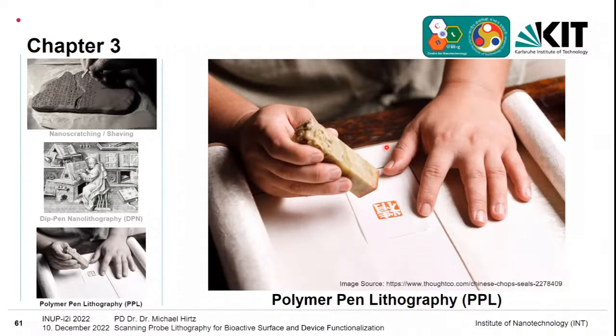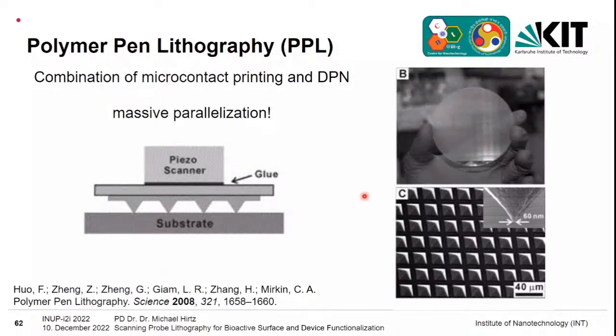Of course, many other places in the world also used stamps, like wooden stamps. And again, we try to miniaturize this and gain control over it, even in the micro or even in the nano realm. This leads to the so-called polymer pen lithography. It's a combination of micro contact printing, which you may be familiar with, and dip pen nanolithography. What it brings in particular is a massive parallelization, because now you attach a polymer stamp to the piezo scanner of an AFM, and you have many pyramidal features on it.